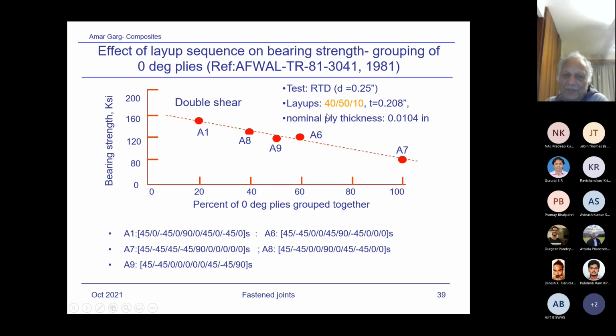So what you see here, the percentage of zeros is 40%. The number of 0-degree plies in each layup is the same. The difference between each one is how you distribute the 0-degree plies. You can see here, 0-degree plies staggered. Here you have 45s together, 90s, and then zeros together. So look at this, A1 to A7. A7 is the lowest, A1 is the highest. So the rule is: spread the 0-degree plies, do not bunch them together.